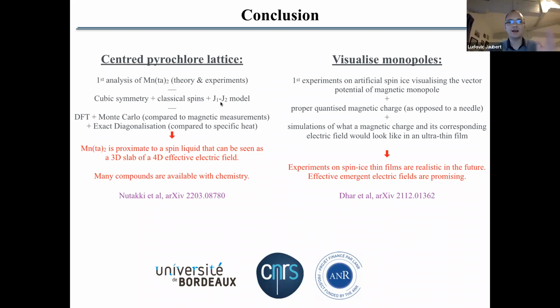And we have shown that the finite temperature properties around 1 Kelvin and above can be well mapped with a simple J1, J2 model, which is in the proximity of a spin liquid phase.